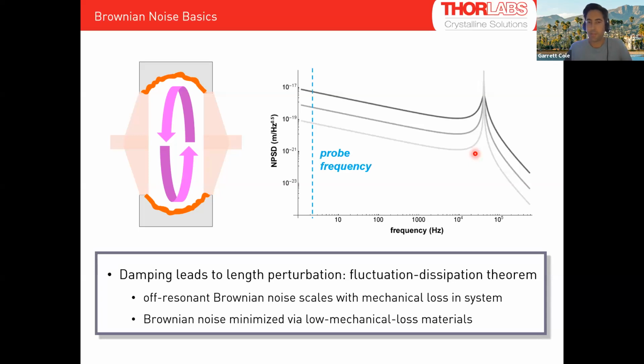In most of these experiments, I'm going to be probing way off resonance, much lower frequency near DC, and these mechanical resonances are going to be way up at high frequency, right? So I'm looking at the tails of this mechanical resonance. And in this plot, I've shown 3 different mechanical quality factors, a low one, a medium one, and a very high quality factor, or flip that, let's say a large imaginary component of the Young's modulus going to a low value of the imaginary component.